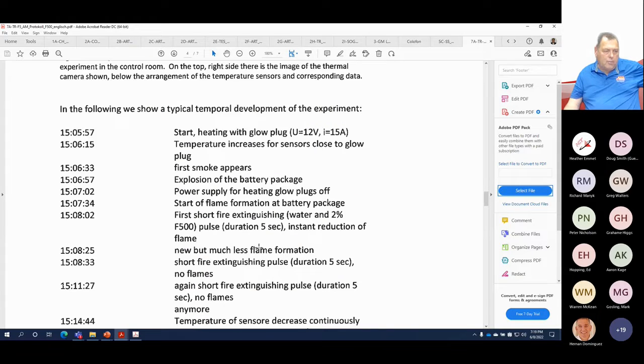Full data. Now this is what I find extremely interesting here: start the heating at 5:57, temperature increases, first smoke appears at 6:33, explosion of the battery pack at 6:57, at 7:02, power supply for the heat glow plugs goes off. At 7:34, we start flame formation at the battery package. At 8:02, we do the first shot of the F500 agent. So it's water and 2%, but a 5-second burst. That's it, just 5 seconds.